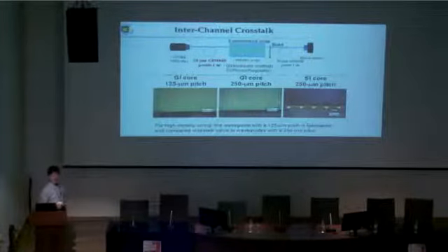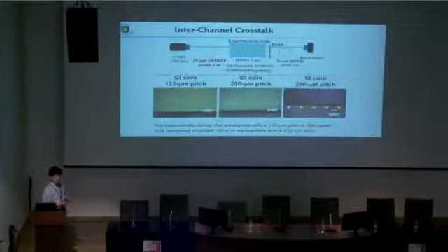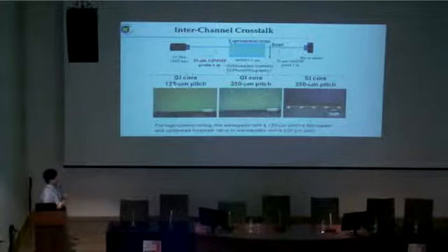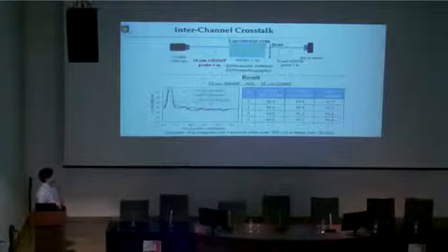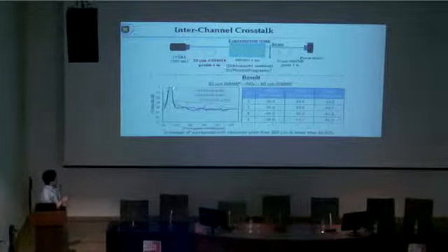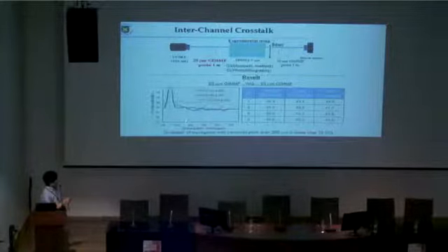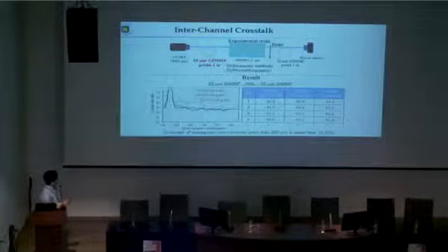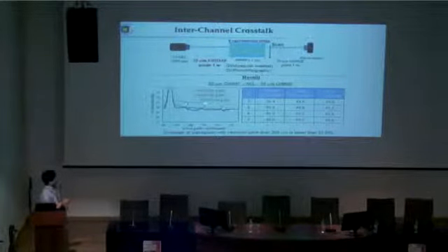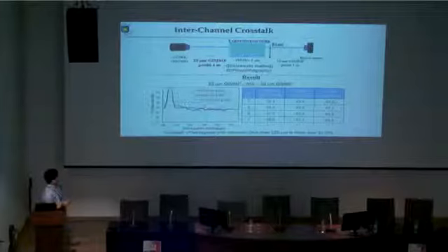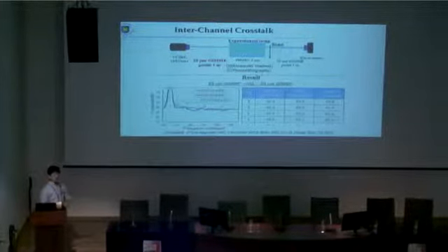And then, in such a narrow pitch waveguide, how much is the crosstalk increased? We evaluated the interchannel crosstalk in this 250 micron pitch GI core and SI core and a half pitch one. Here is the result. This is the optical power from the launched core and adjacent cores. In the case of 250 micron pitch, the adjacent core is here, and the second one, third one, and 125 is in the middle. You can see higher output power from the SI core waveguide, not only from the core but also from the cladding. It is very interesting that at the core, the output power suddenly dropped in this way.